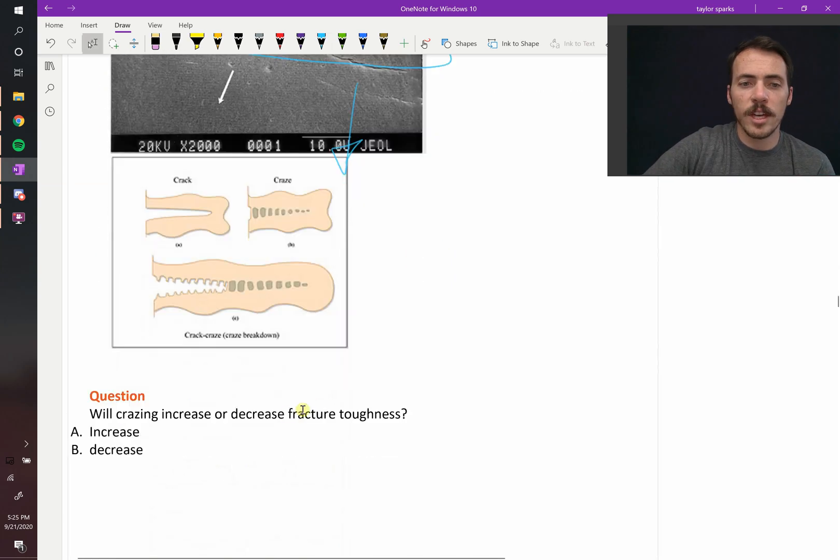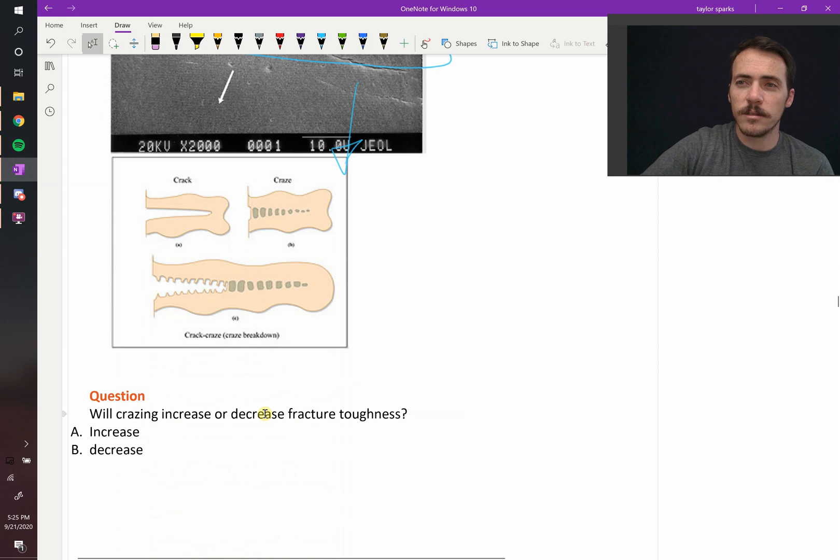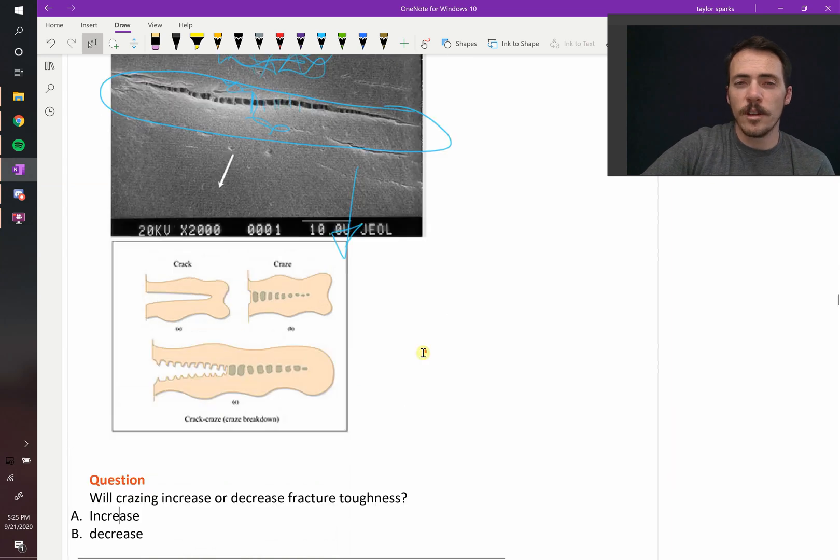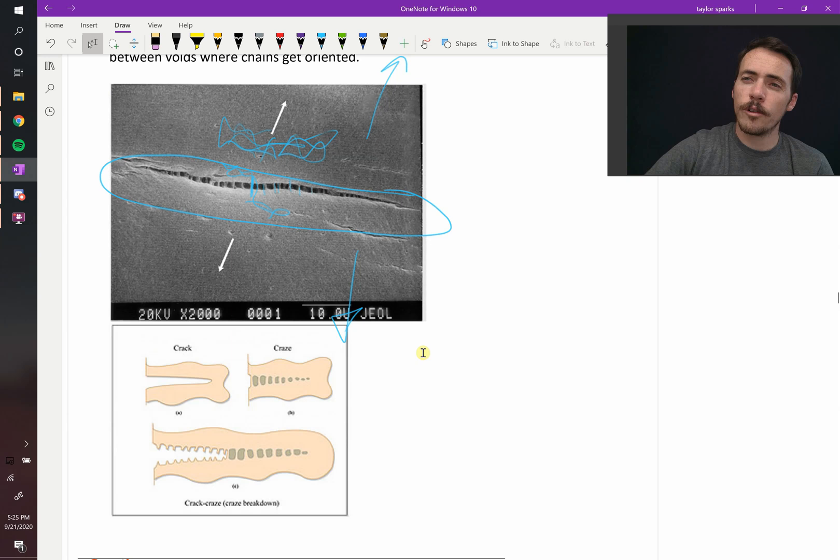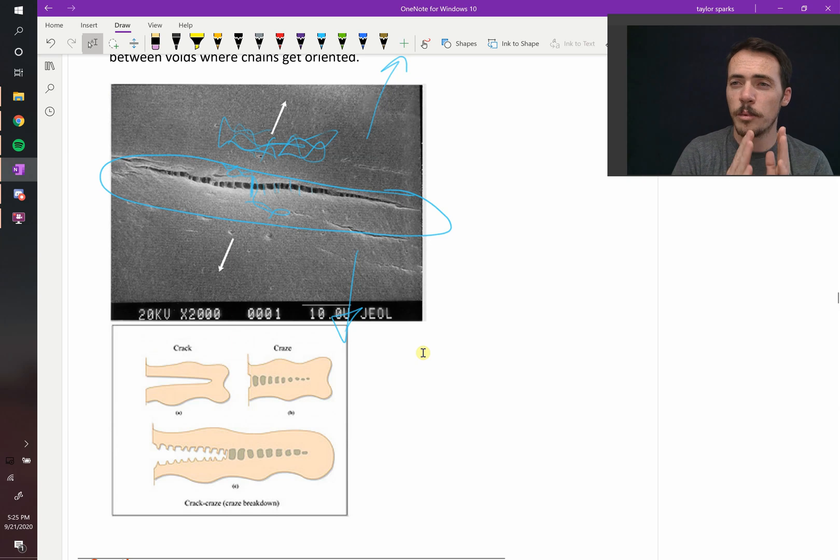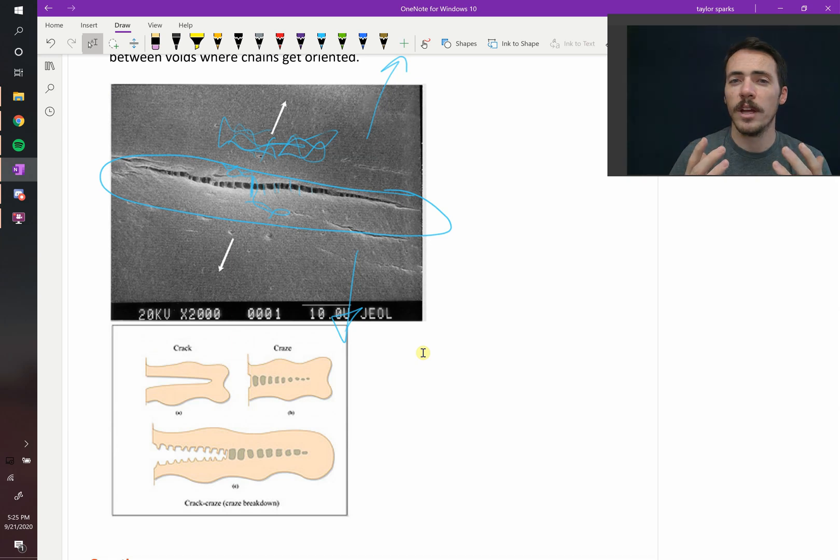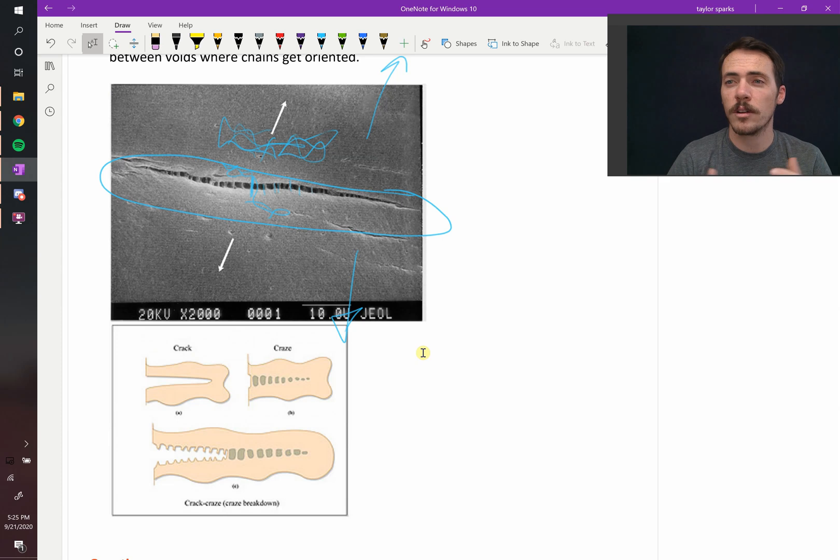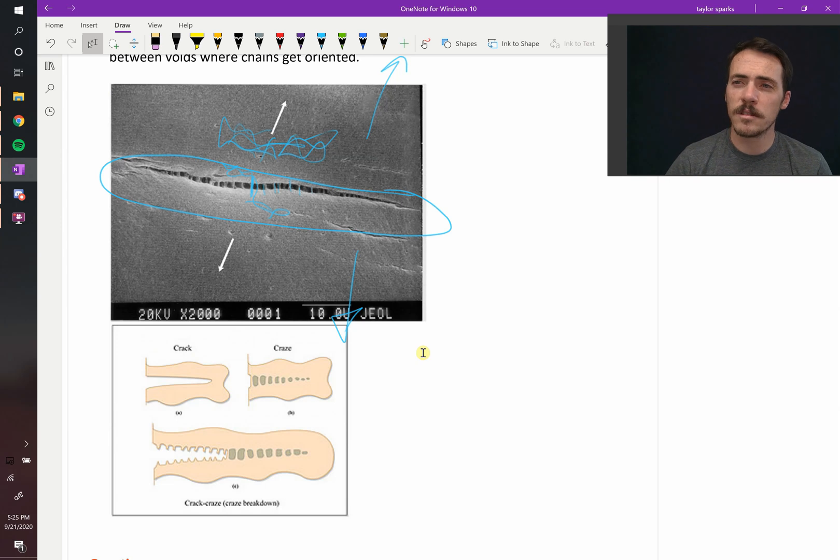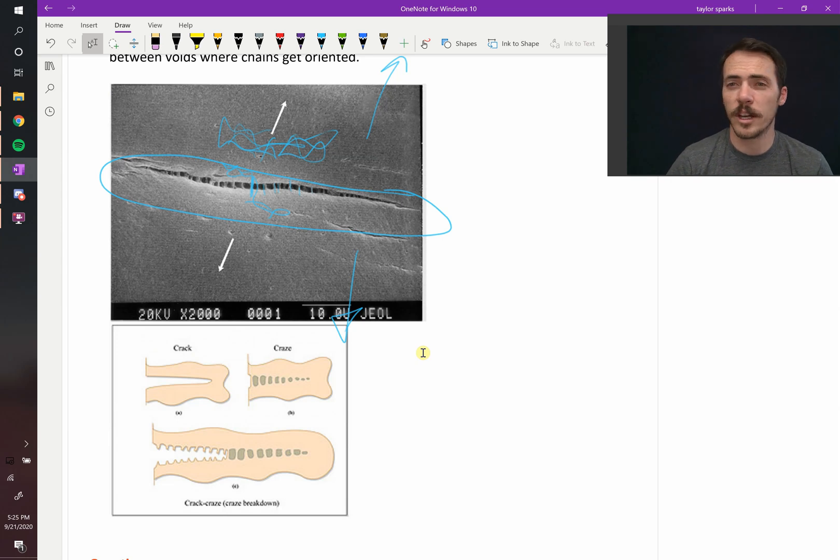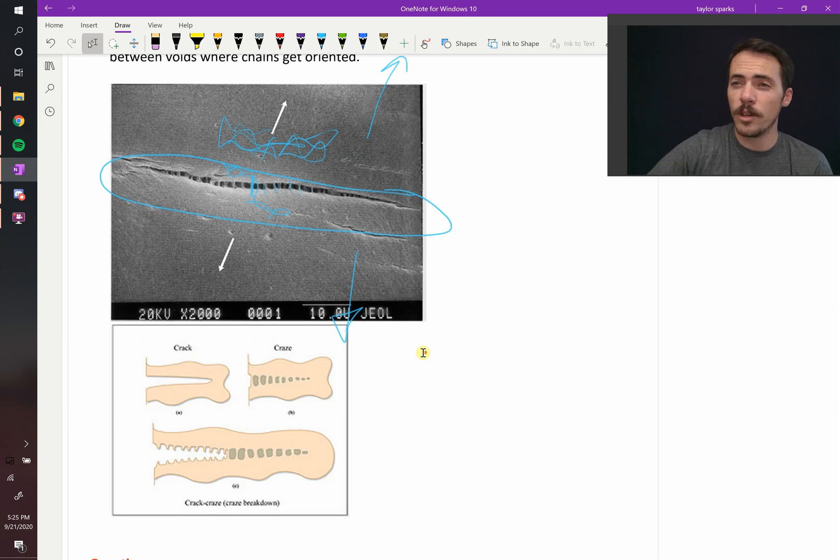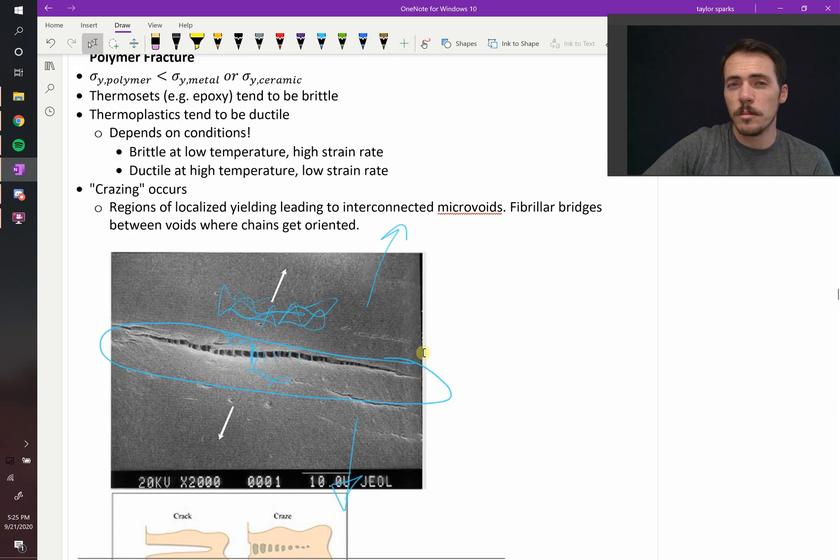Hopefully you wrote that it increases it. This should, if it makes it harder for a crack to initiate or propagate, you've made a tougher material. Since this makes it harder for both, for initiation and crack propagation, polymers in some instances can be relatively and surprisingly tough. They can absorb a fair bit of energy as you go about breaking them into two components, even though their yield strength isn't much to speak of.